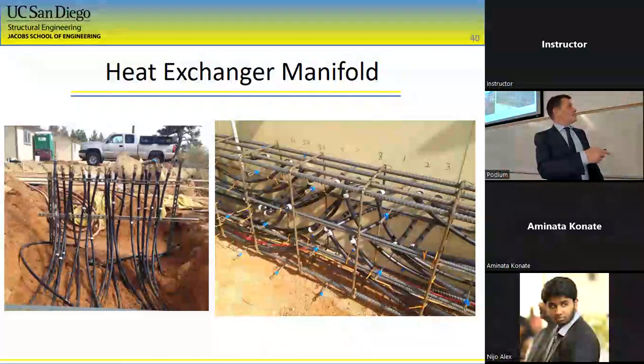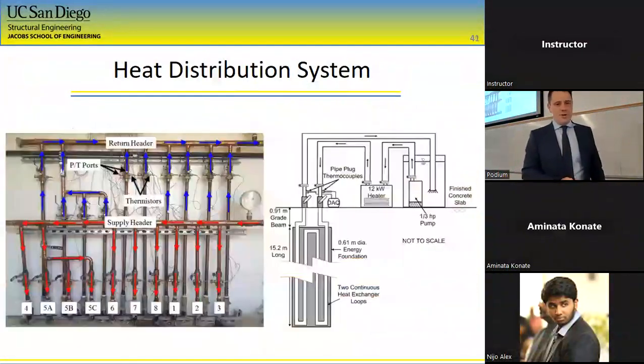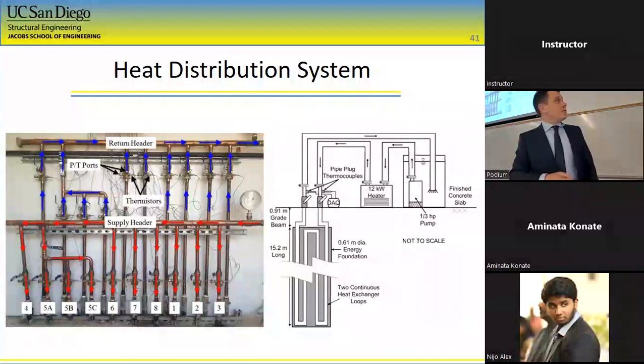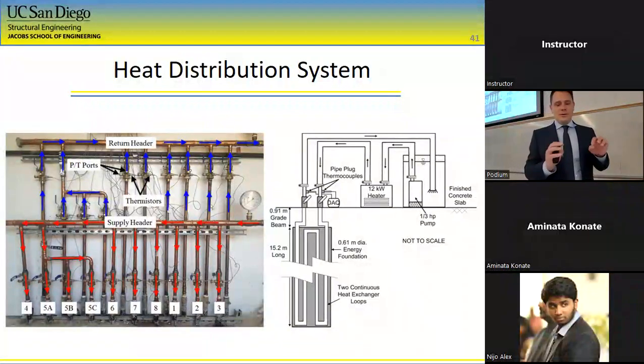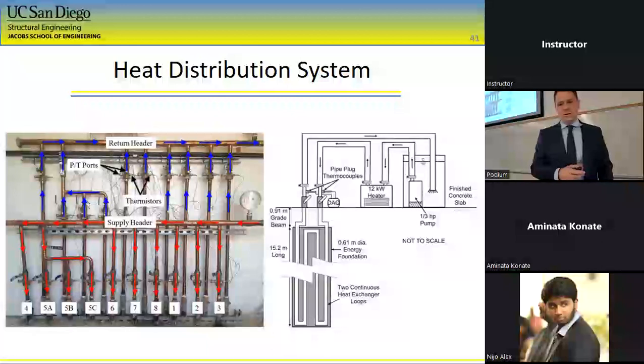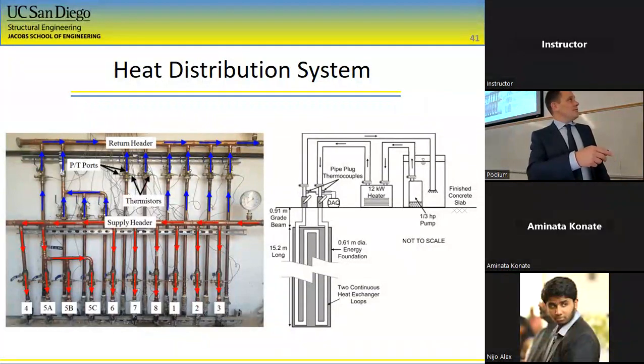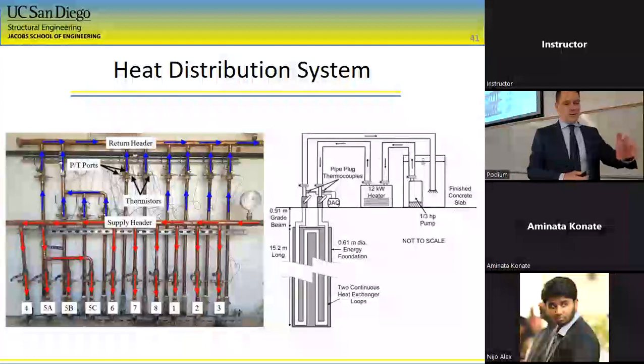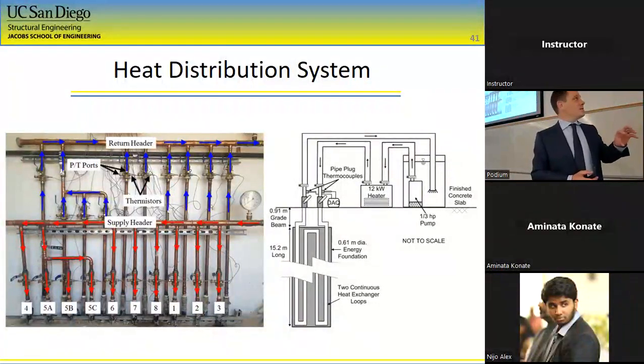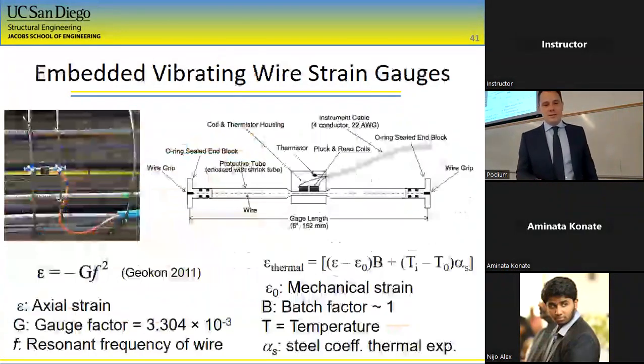And this was where we were able to inject the hot water from our heat exchanger. So we have the hot water going into one side of the header, goes down into the pile, comes back up onto the return header. We measure the temperature of the fluids going in, temperature of the fluids going out, and the flow rate through each. And from those sets of information, you can get the heat transfer rate. And then we just used a very simple case where we had a bucket of water and one of those tankless hot water heaters that provided a constant heating rate, and heated each of the piles and did a thermal response test.